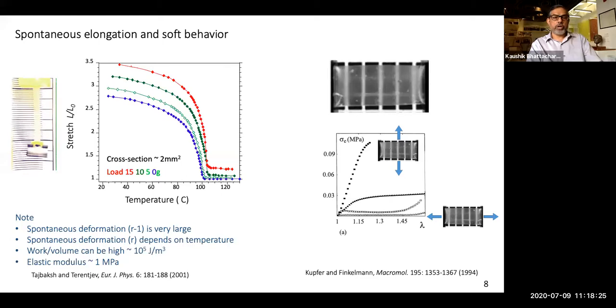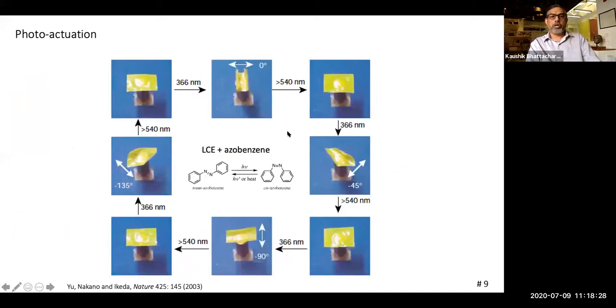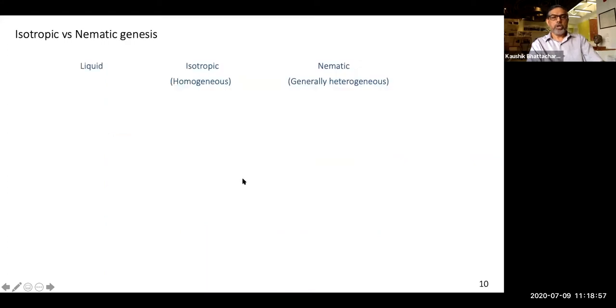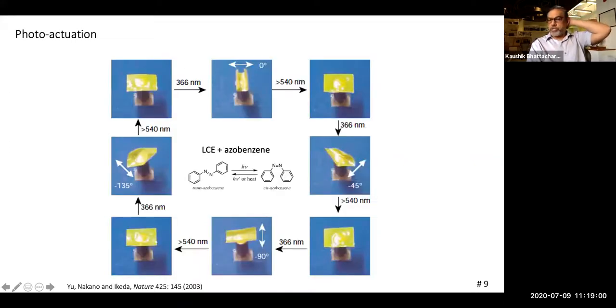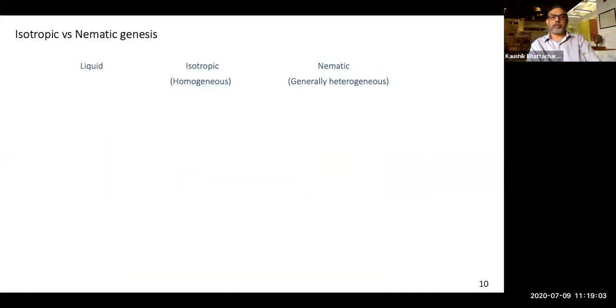So let's try to, and that's what I wanted to show, this is an old experiment of Ikeda, where he puts photoactive azobenzene into these materials. You shine light, it begins to curl up. You shine light of a different frequency, it comes back flat. And the fact that if you change the polarization, the actuation angle changes shows you that the actuation is directly by coupling to light rather than light heating up the material. So this is what I want to describe. This is the kind of behavior I'd like to try and understand and build models for.